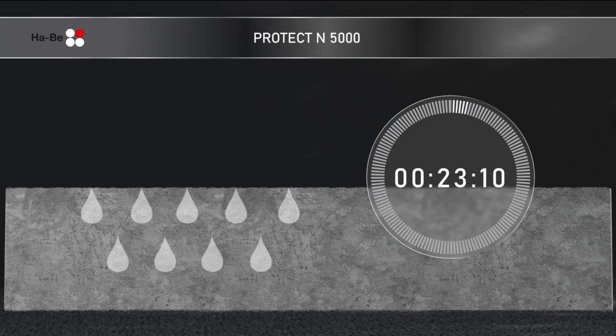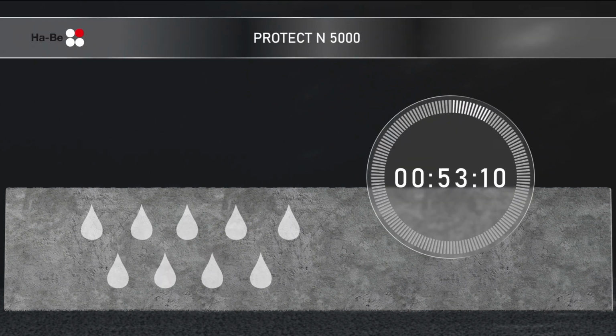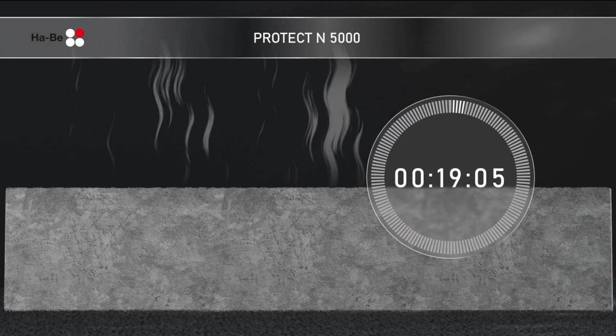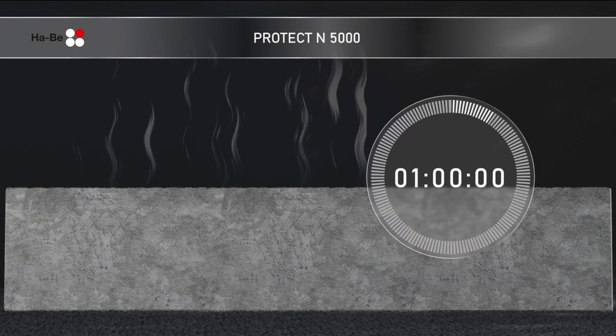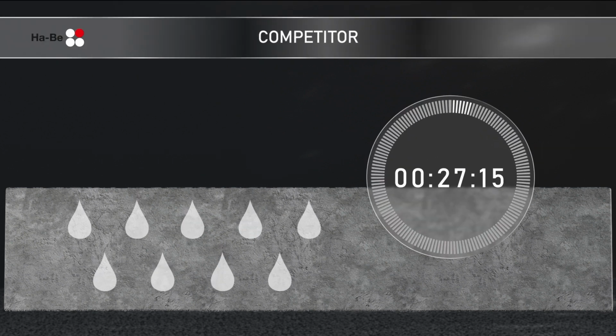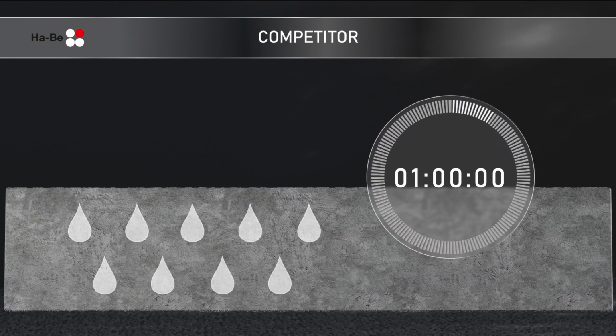Material C weakly retains moisture from penetrating into the concrete, but allows the penetrated moisture to evaporate well through the hydrophobic protective coating. Material D doesn't retain moisture from penetrating into the concrete and doesn't allow penetrated moisture to evaporate through the hydrophobic protective coating.